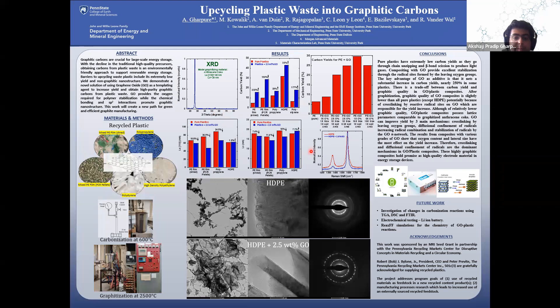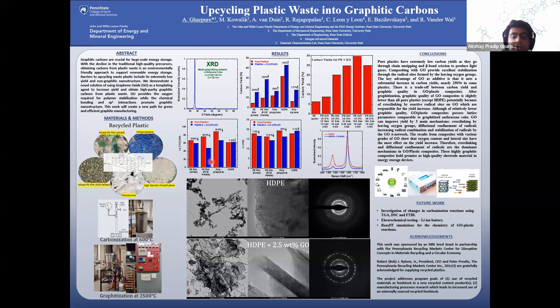X-ray diffraction, Raman spectroscopy, and transmission electron microscopy were used to assess the graphitic quality of the carbons. After addition of graphene oxide, the graphitic quality as gauged by crystallite parameters L_A and L_C increased for the high-density polyethylene but decreased slightly for the rest of the plastics. A trade-off was observed between carbon yield and graphitic quality, as cross-linking stabilization provided by graphene oxide may have restricted the growth of the crystallites. The obtained carbons were highly graphitic, with crystallites comparable in size to those in the model graphitizing material anthracene coke.